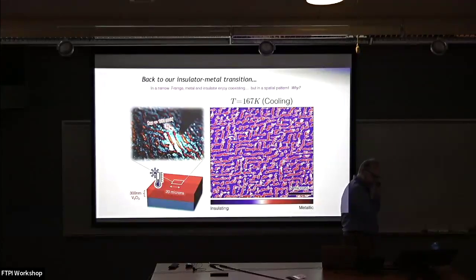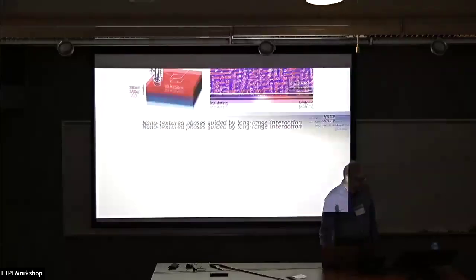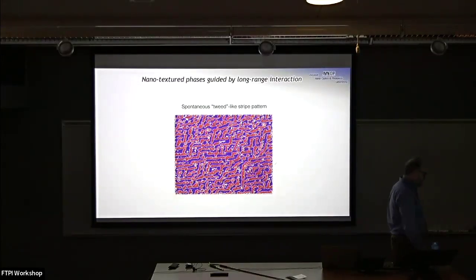All right. And some of the first questions that I get about this movie is what the heck is the deal with these stripes and so forth. Presumably, if one did a diffraction probe, you would see some exceptionally low correlation in the order here. Of course, what we're seeing here is in real space. So let me comment a little bit on that, because it's a useful reminder, I think, especially for the experimentalists in the audience, that long-range spatial correlations, in some cases exceedingly long-range spatial correlations, are a consequence of some physics that we should always bear in mind when it comes to phase transitions, first order or second order.